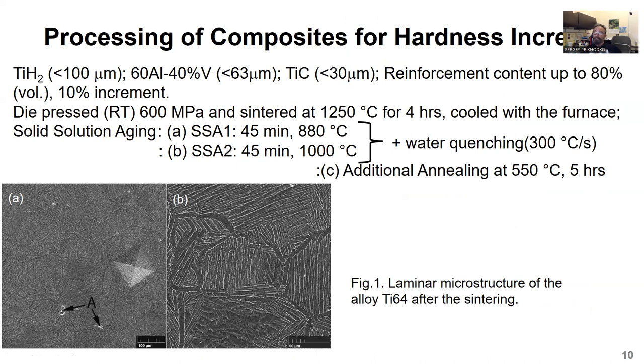The reinforcement content was varied in this study up to 80%. The modification of the phase composition and morphology of the base alloy can be done through high temperature aging. Our base alloy Ti64 has a two-phase lamellar alpha-beta structure with beta phase making up about 6% and the average beta grain size close to 100 micrometers. The idea was to use high temperature aging to increase the beta phase amount and further transform it after quenching into a very fine alpha plus beta mixture.